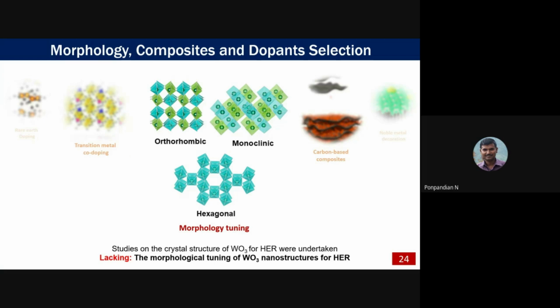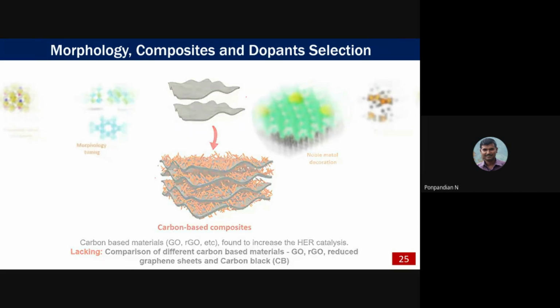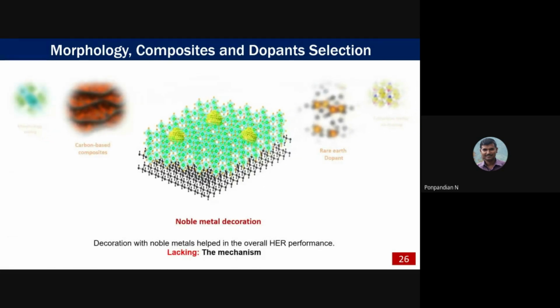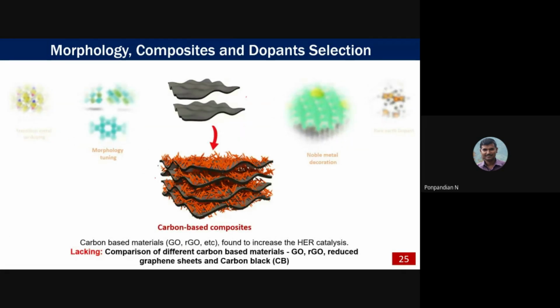Again, what we wanted to do is the tuning of the morphology, the morphological tuning of tungsten oxide nanostructure for hydrogen energy. For that, the next slide, you can go to the next. Here, what we are doing is we are making the first step. What we are doing is the basic is actually the tungsten oxide. In addition to the tungsten oxide, we are adding some 2D materials. That is actually the graphene. Graphene is a 2D material.